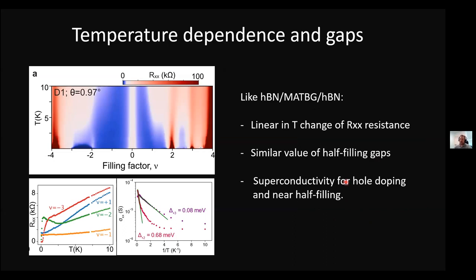With this device, you can measure activation gaps. You can also acquire more detailed temperature dependence. You can verify that there is a linear in T scaling of Rxx. And all of this just tells you the physics is effectively not changed from your usual HBN encapsulated twisted bilayer graphene.